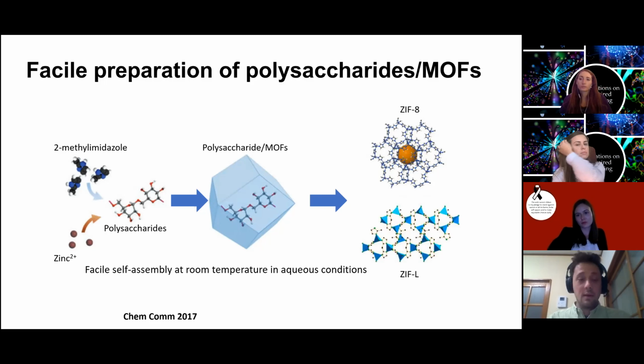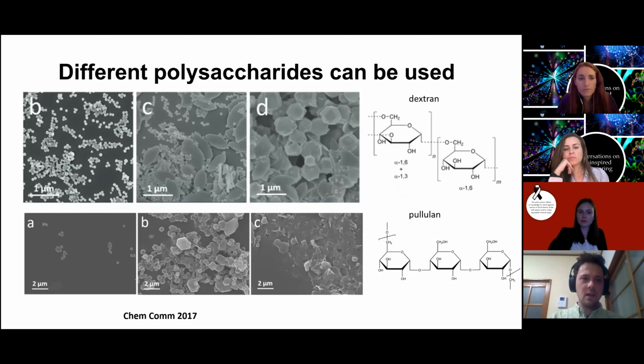Sort of like using food analogies, because it's very early in the morning, when you mix eggs and flour, you can turn them into pancakes, you can turn them into bread, you can turn them into cupcakes. It's the same building blocks, but you get different forms out of it. So we can use different polysaccharides, which will also control the structure, but we use dextran here, we use pullulan, and as you saw, we just vary the concentration as we move right. It's not too important the exact conditions, but the crystal size and the crystal form change as we vary the